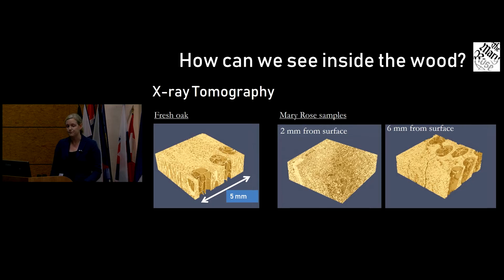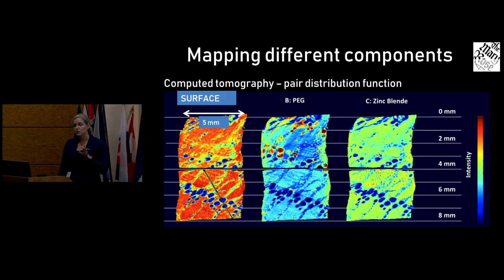is less degraded. Now, what's fabulous about ID15 is that at every voxel within that tomograph, you can take PDF analysis. Now, PDF, very briefly, as opposed to XRD, is going to tell you about all the nanocrystalline and amorphous phases that are there. So what we're able to show here, this is a slice through a core sample. So on the left, you have everything that's there. What I really love about these images too is that you can see the growth rings, and you can also see that either the plank or where we took the sample is obviously not straight on, it's slightly off.